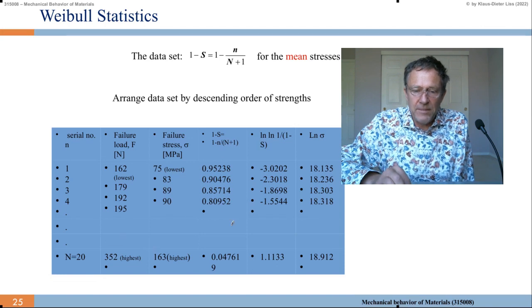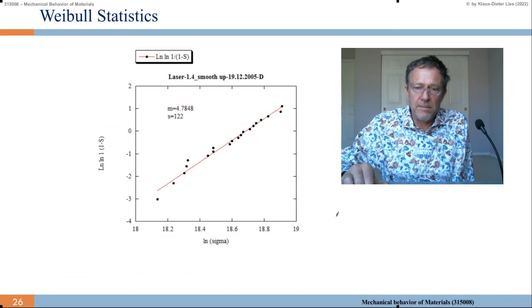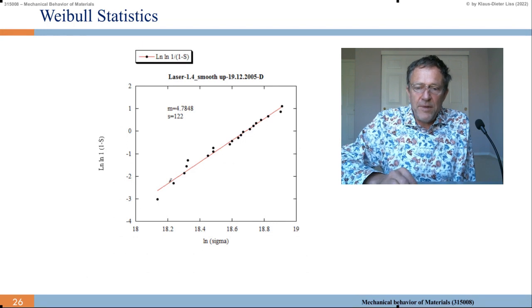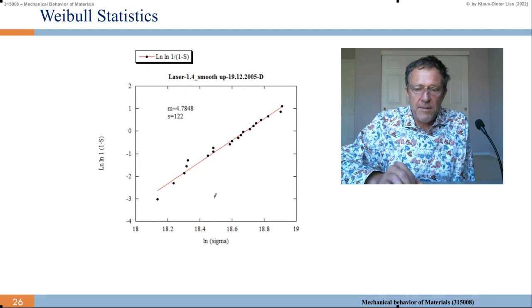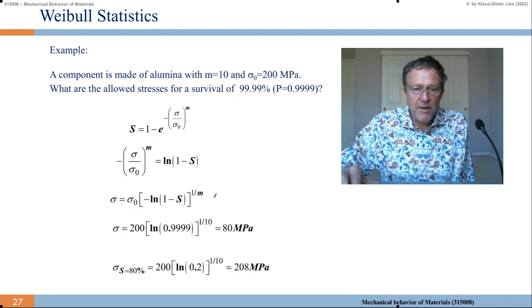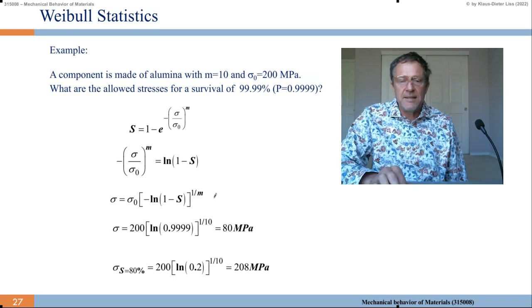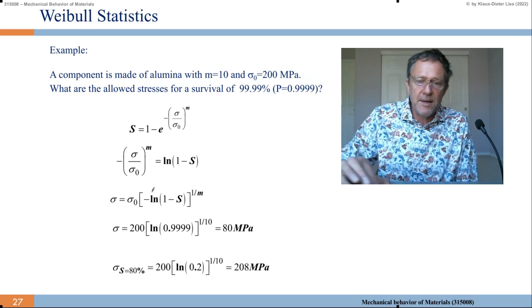These values, and then the ln sigma, the sigma is here, so ln sigma becomes those values, and you plot them. You plot them, you fit the line, m in this case becomes 4.7848, and the sigma 0, or s, they call it here, is 122, and from that you can work it out. Here, another example, another exercise, typical exercise for exam questions.